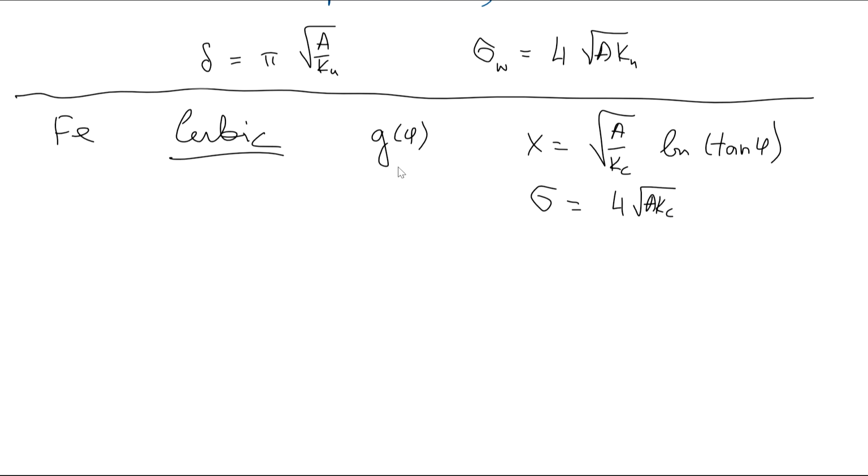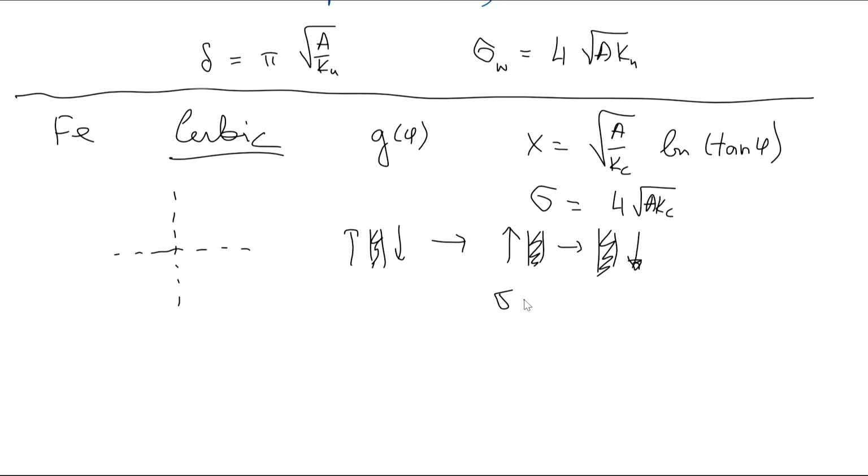Now, the way you calculate it for cubic anisotropy, there are two easy axes. So there is an easy axis pointing this way, an easy axis pointing that way. And therefore, instead of having a 180 degree domain wall, you separate that into a 90-degree domain wall, plus another 90-degree domain wall. So the energy would be combined of a 90-degree plus another 90-degree domain wall. And you saw that closure domain for iron.